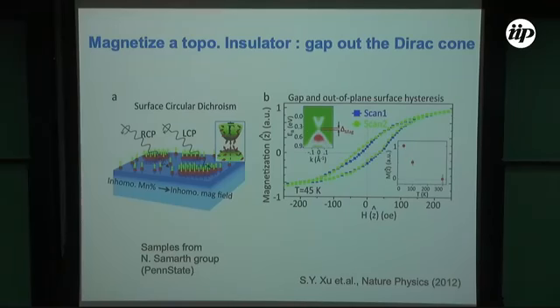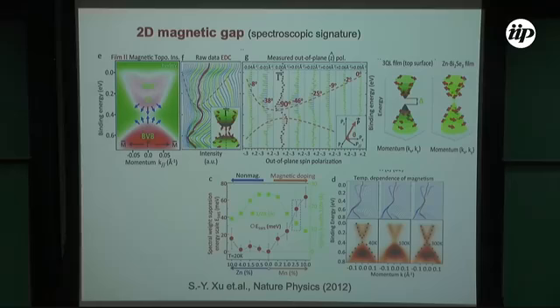Now we can see that there is a gapping behavior here, and the nice Dirac crossing is lost. This is correlated with the fact that there's a surface magnetization that we can correlate with the presence or absence of hysteresis. We can do finer experiments to understand the origin of the gap, because there could be some extrinsic origin of the gap. So what we did is dope these topological insulators with non-magnetic impurities and magnetic impurities, and see under what conditions the Dirac cone is destroyed.